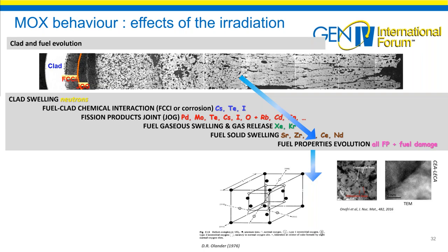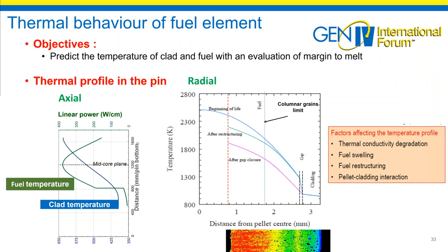Now, a description of the temperature in the fuel element. First, the purpose of this assessment is to predict the clad and the fuel temperature with all the evolutions we have just listed. The axial temperature profile results from the linear heat rate axial profile, with a maximum named the max flux plane, close to the mid-plane of the core. The axial fuel temperature, in green, follows this linear heat rate profile. For sodium fast reactors, the circulating coolant from the bottom to the top of the pin will heat by about 150 degrees in contact with the hot fuel elements. The clad temperature, in dark blue, will actually increase from about 400 degrees up to 600 degrees at the top.